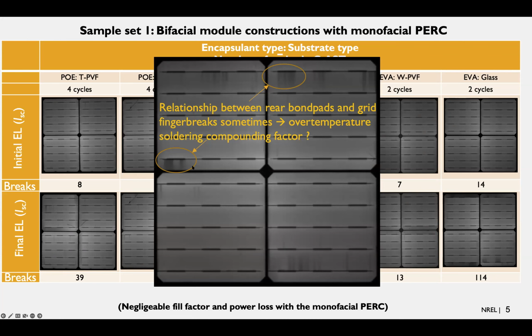The fundamental origin of these kinds of grid finger breaks, or the weaknesses, might be potential over-temperature in the soldering, which leads to embrittlement. But that wasn't the case through all the different samples in the experiment. It really seems to be, based on the data, that the glass substrate was what finally precipitated the increased grid finger breakage.